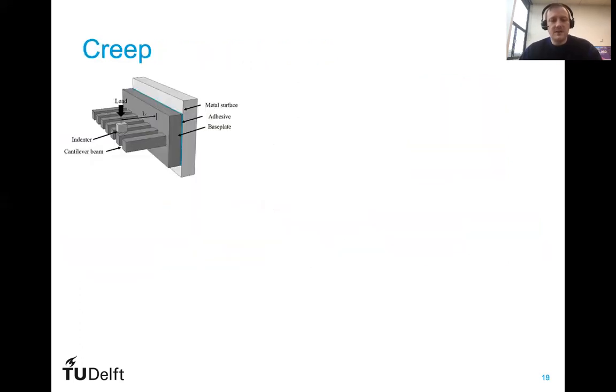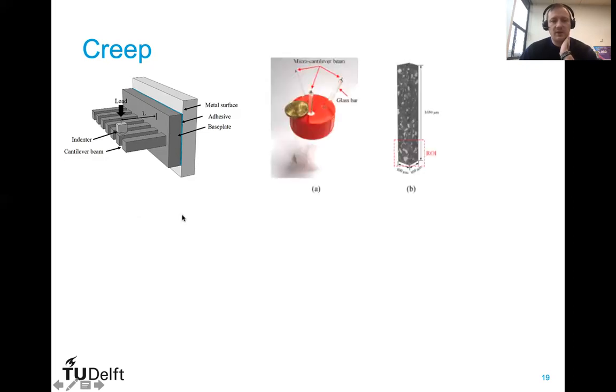We have then expanded this framework to simulate also time-dependent phenomena in cementitious materials. A first example that I will show here is creep. As we know, cement paste is sort of a viscoelastic material that has increasing deformation with constant load over time. And then we use the same framework, same experiment. So we have cementitious matrix specimens cut here in the form of cantilevers. Then we load them using a nanoindenter.